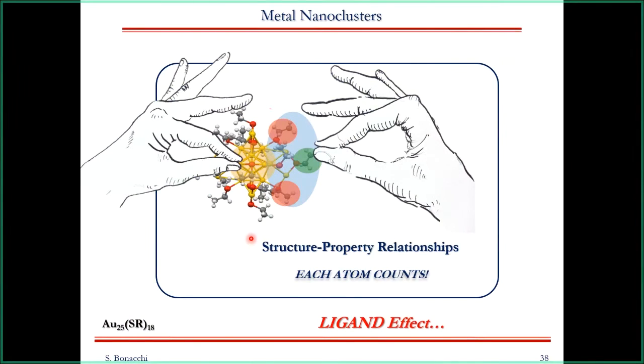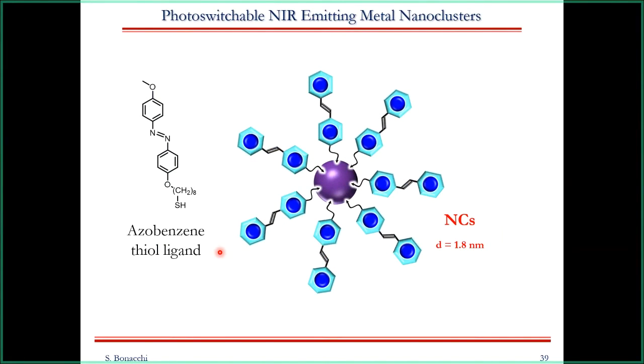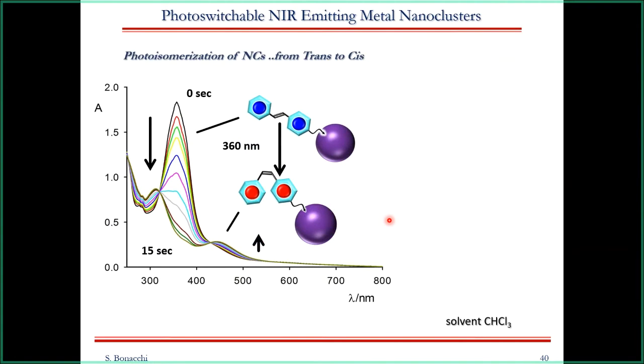Let's see now an example of what we can do by playing with the ligand. So before we play with the composition of a kernel, let's look at what we can do if we play with the ligand. For this purpose, I would like to show you this nice study in which we functionalized nanocluster with the azobenzene thiol ligand, so with this very famous photoswitchable moiety, again characterized by quite a long alkyl chain to reach the core. So this is the structure, let's say the cartoon of the structure, but it was well characterized.